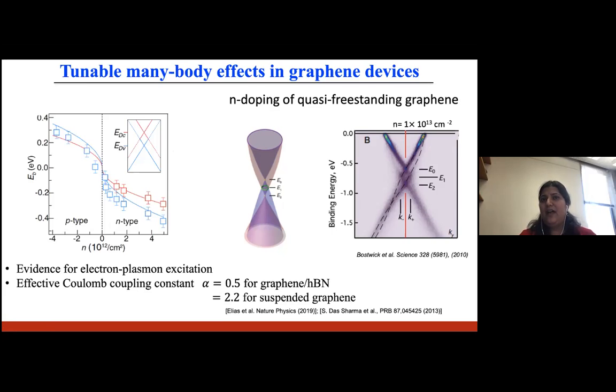And even though the value of alpha looks small, we find that electron-electron interactions can be rather large, as was seen in this previous study. And just for reference, for suspended graphene, where it is fully unscreened, the coupling constant was estimated by these two studies to be about 2.2. Okay.